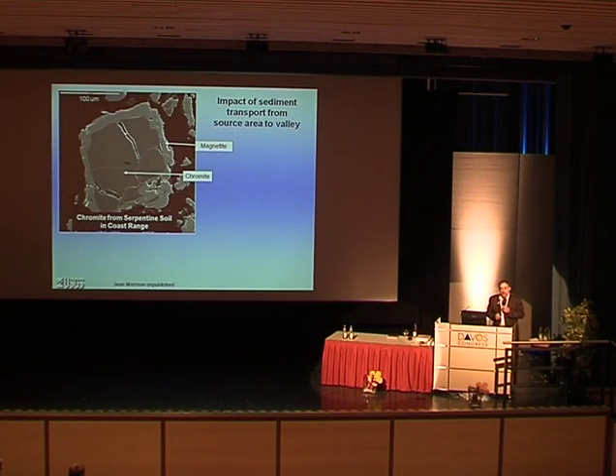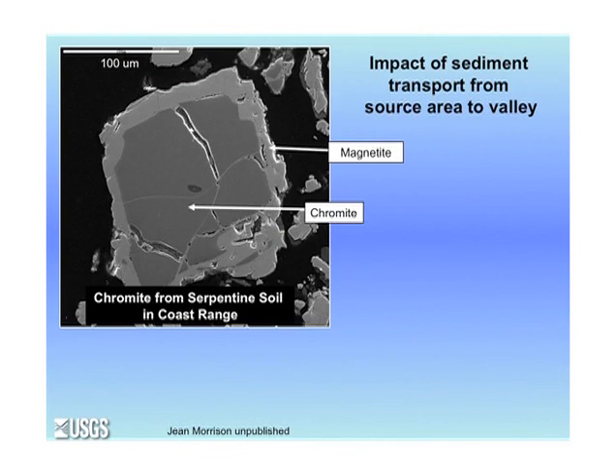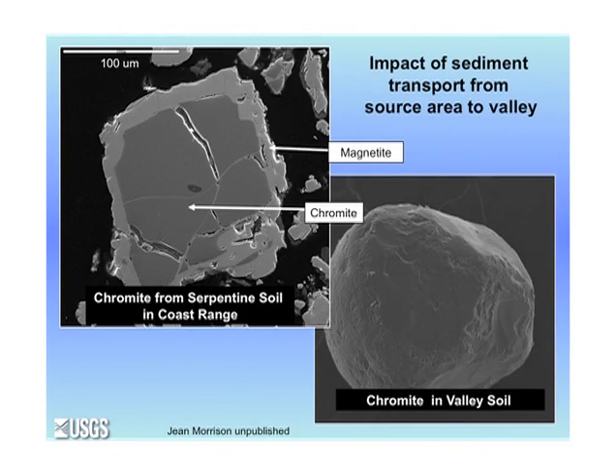So what we're going to do now is consider the consequences of transporting chromium from an ultramafic rock up in the coast ranges down to the Sacramento Valley. So if you make a magnetic separate from soil that's overlying the ultramafic rocks up in the coast ranges on the west, you'll get a lot of material. But if you look at it in the scanning electron microscope, you see no chromium at all, or virtually none. The reason is, if you make a polished grain mount, and look at the cross-section of the grains, what you see is chromium in the form of the mineral chromite, an iron chromium oxide, which is the dominant residence for chromium in these rocks, is mantled by magnetite. And that's why you can't see it unless you cut through the grain.